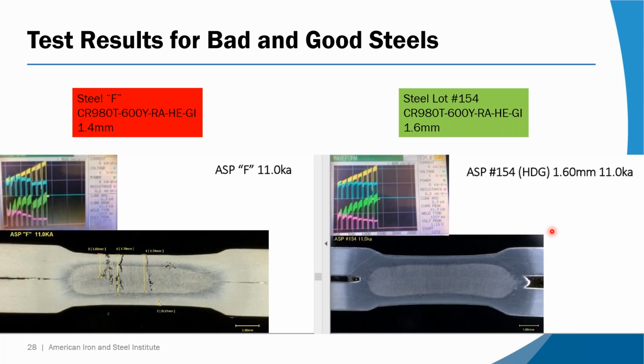There's something basically different. Okay, now the one on the left has a drop in the voltage curve at, what is that, so either between the 5th and the 6th pulse, and that translates, if you look at the power curve, a big drop in power there because it's the product of current times voltage.